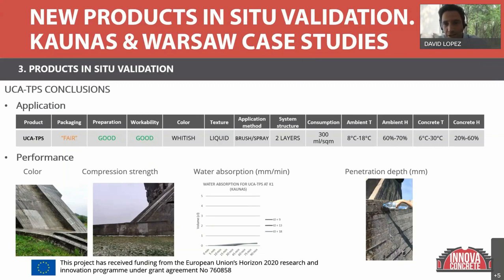And sometimes nature gives us other solutions that are much more visible and much clearer. Here I just want to show that, for example, during our visits to Kaunas, the first two visits after 9 months and after 13 months, we had rain and snow. No? And here you can see clearly that this product was working beautifully, because the places where it was applied were completely dry, and they showed clearly.